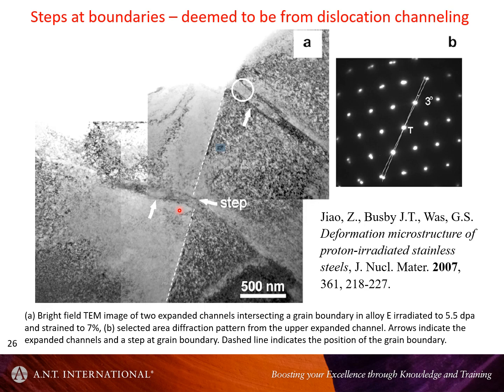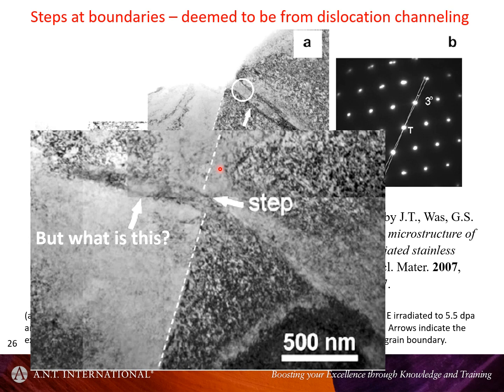You know, so I would look at this, and my first reaction would be, yeah, this looks really interesting and odd. This is a very odd kind of structure. There's a diffraction pattern from this area, and because of this diffraction pattern, they deduced that this was not a twin, for example. But it doesn't look like a channel either. I don't know what it is. If you look at this in a bit more detail, you've got something here. What is it? I really don't know. There is some tilt orientation, but they attributed that to slip, which makes no sense whatsoever, because slip is a planar translation. And to get slip to change the orientation of a crystal, it has to be a subgrain boundary.